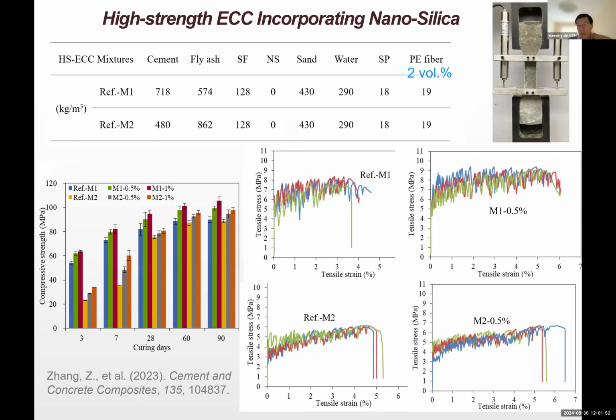Now, yet another example is the high strength engineered cementitious composite incorporating nanosilica. We use a high strength PE fiber, 2% by volume, and then you can get to a compressive strength of more than 80 megapascal at 28 days. And then you typically get between 4 to 6% tensile strain. So it's a strain hardening composite material, especially the reference M2, which uses more fly ash than cement. So you can consider it a high volume fly ash concrete. With 0.5% nanosilica, the behavior is further improved.